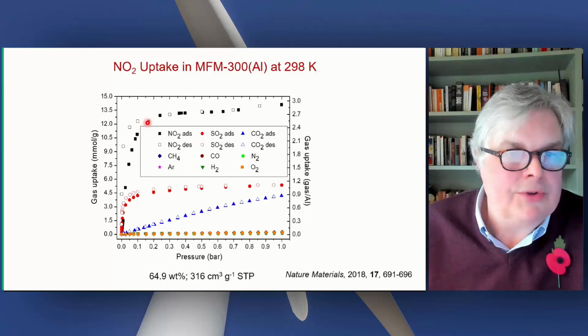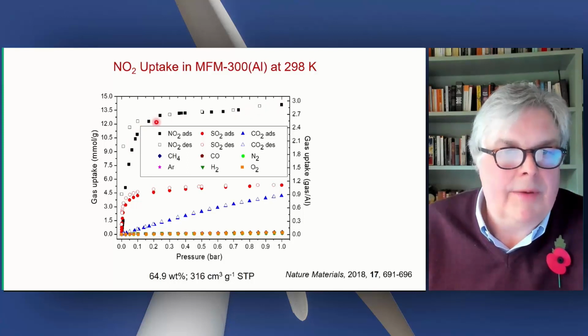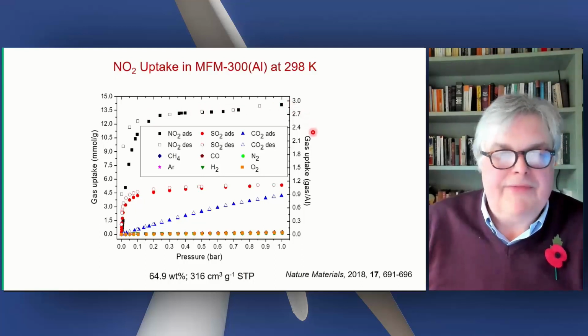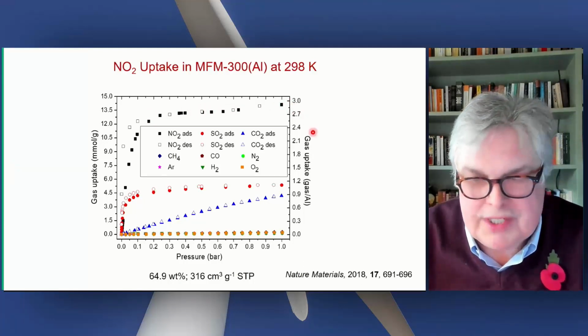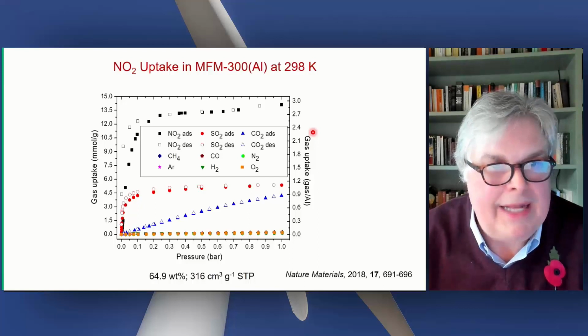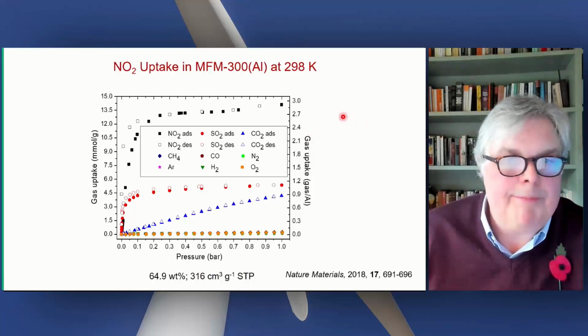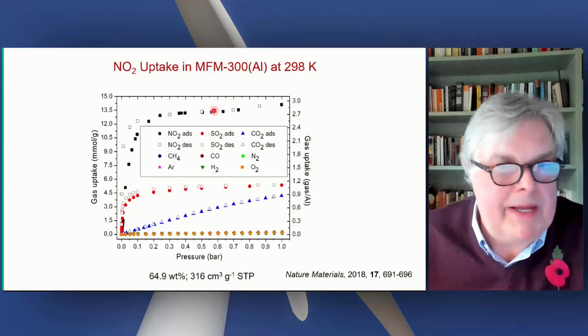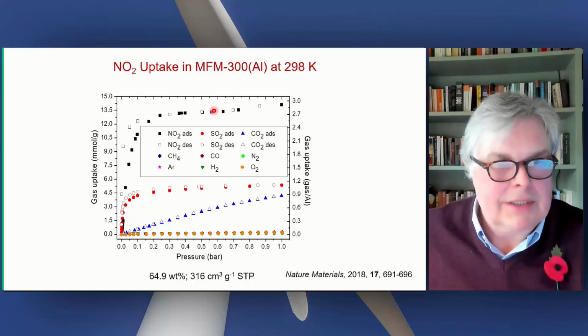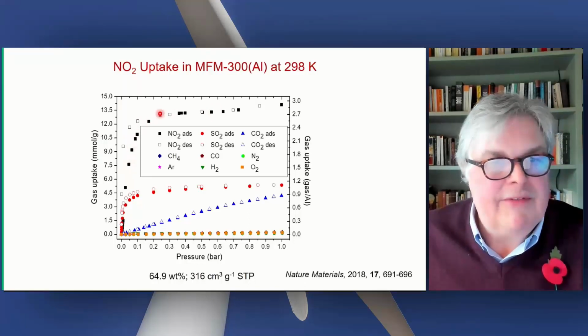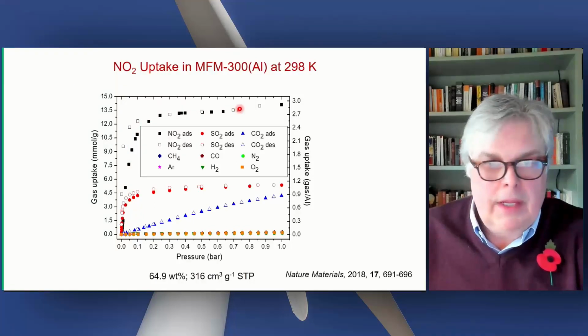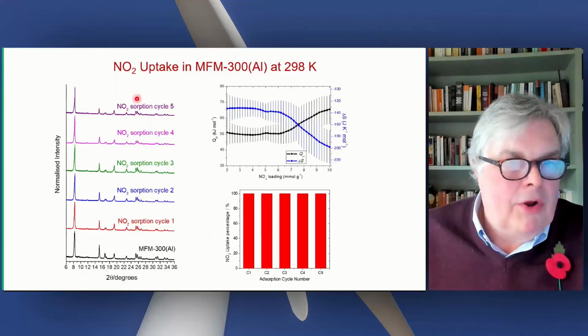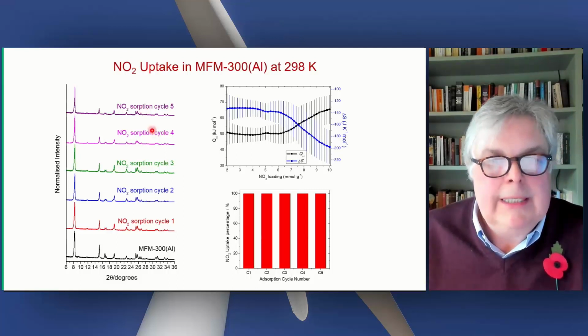This is the NO2 uptake isotherm. In order to get this isotherm, we had to modify our equipment. If you imagine, all the seals, the tubing have to be NO2 resistant. This practically was extremely expensive and also very difficult to achieve, but we have achieved it. This plot shows stability over 5 cycles for NO2 in the aluminium MOF.